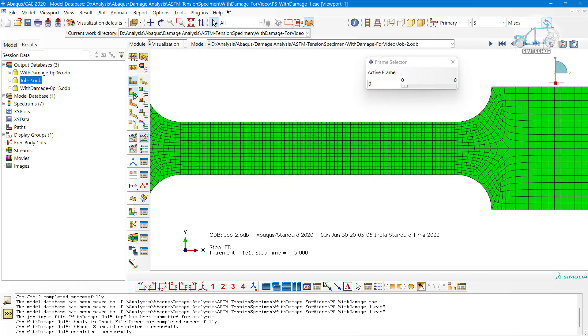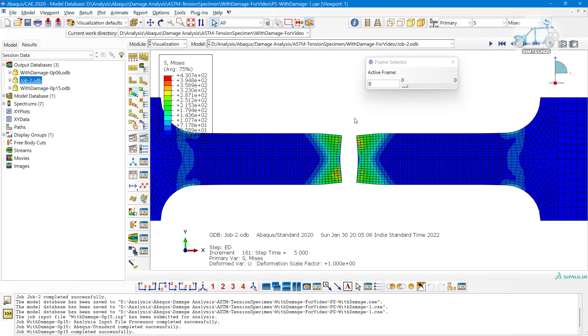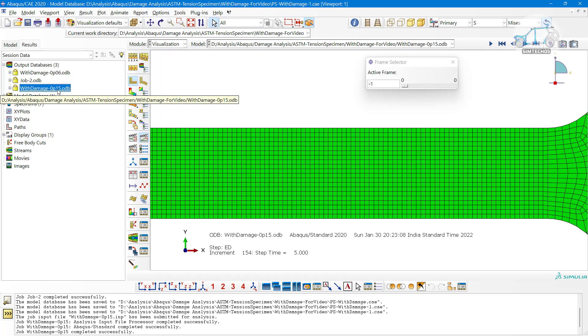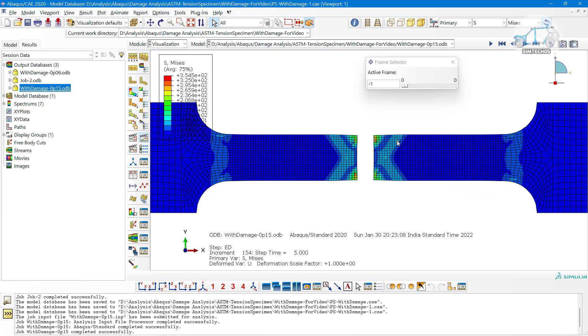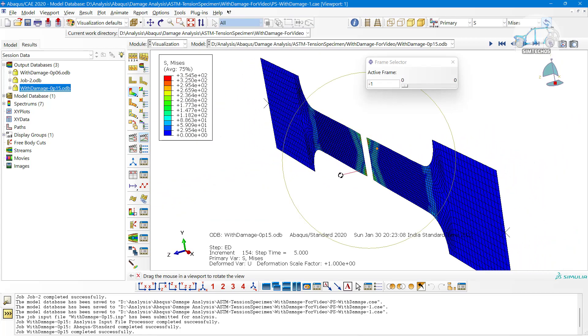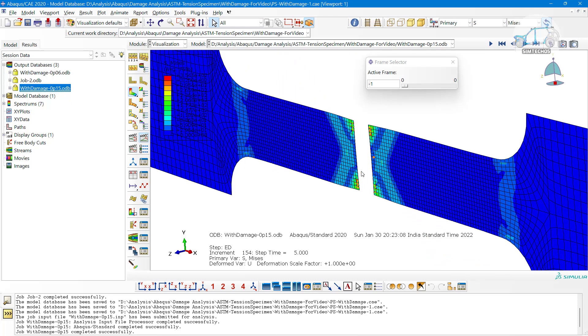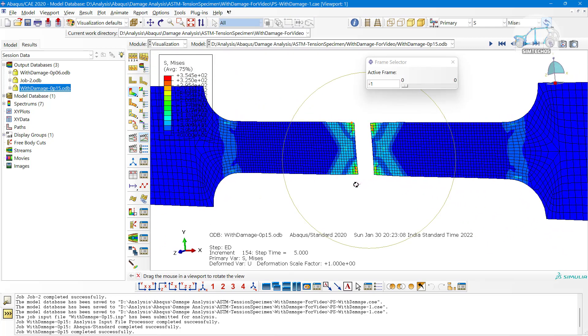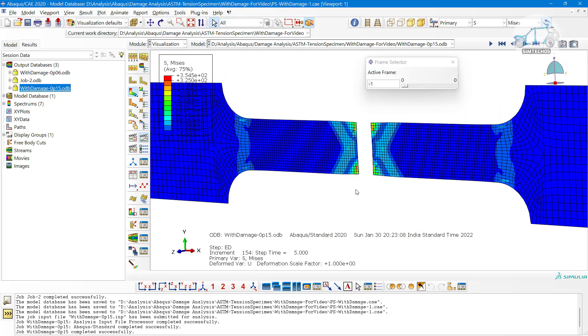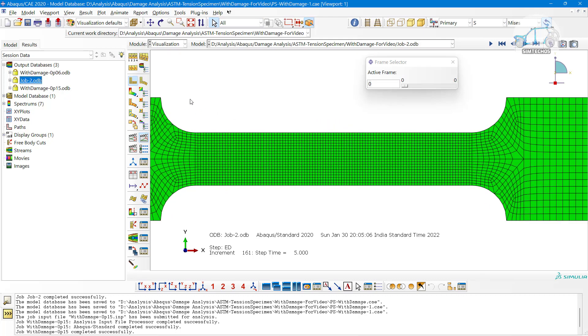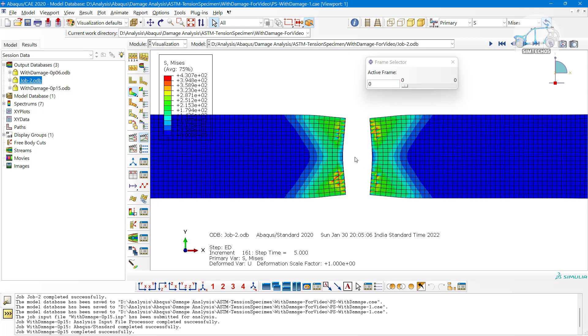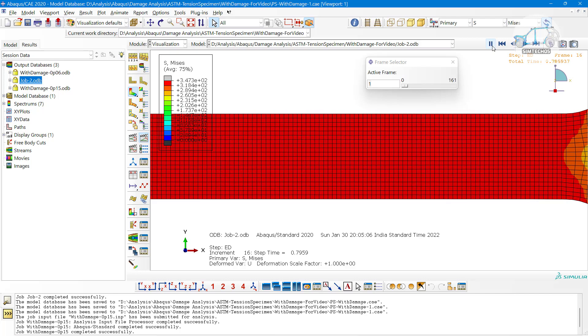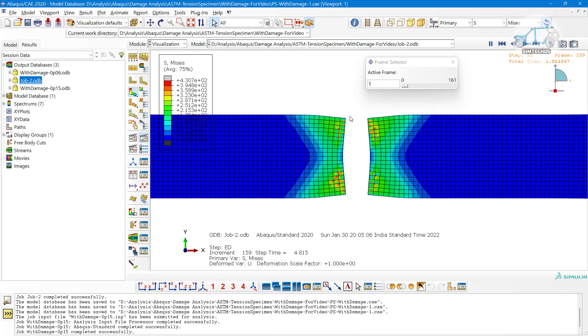In the third case, if you define more fracture strain, it will show you the necking effect also. Of course the necking effect should also appear in the fracture strain 0.15 case, but why it is not visible properly is because we consider here the plane stress condition. The plane stress condition means the component thickness is very less. So if you don't have much material in the thickness direction, it will obviously affect the necking behavior. If you want to see the proper necking behavior, you must go with the 3D component. Here the fracture strain value is quite high — it is around 0.4.